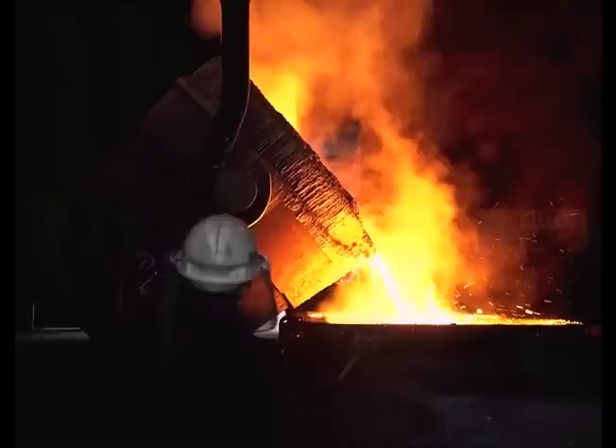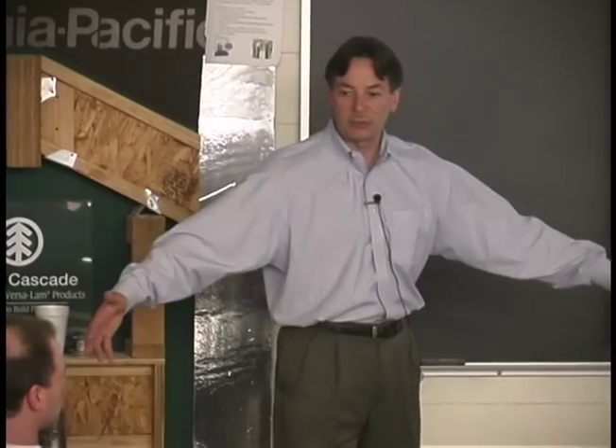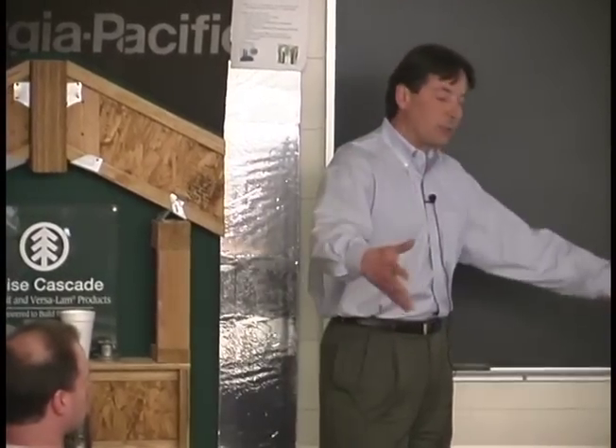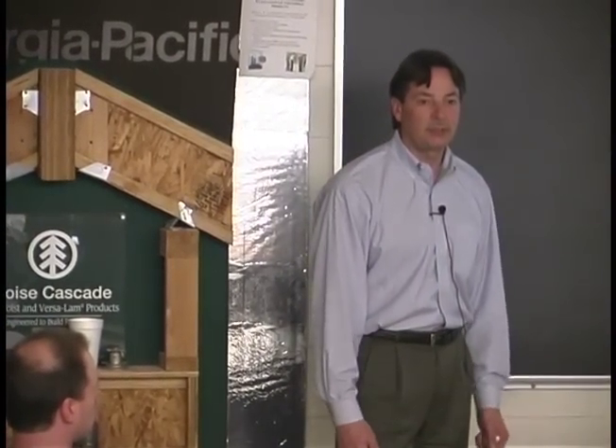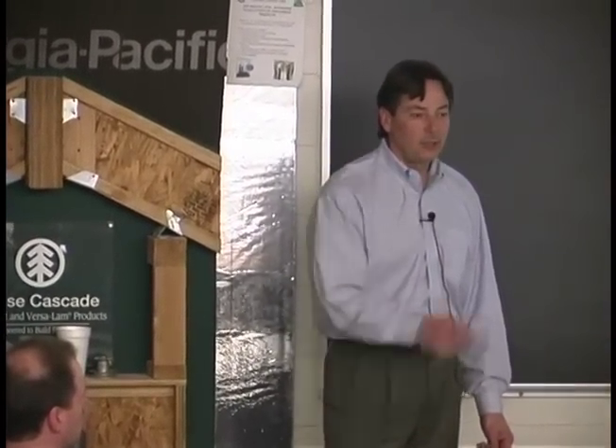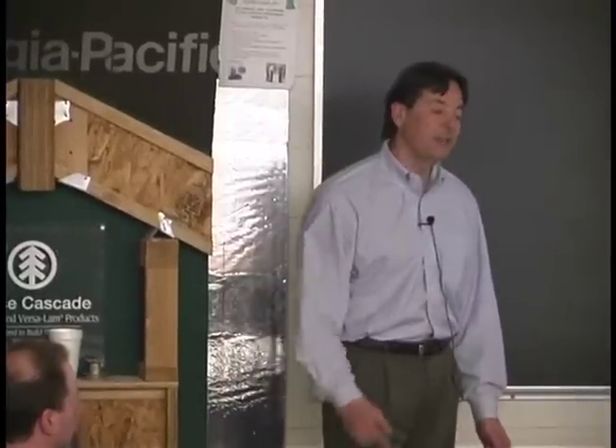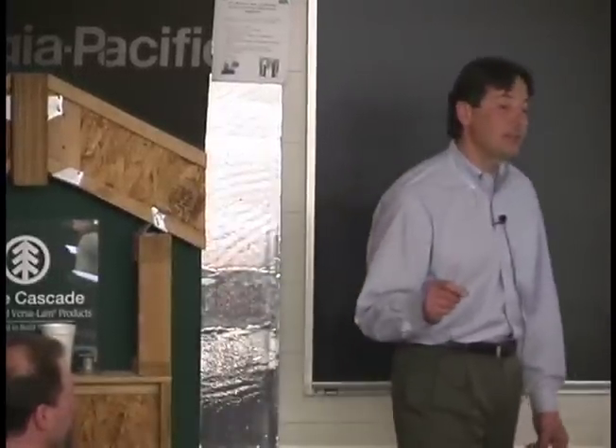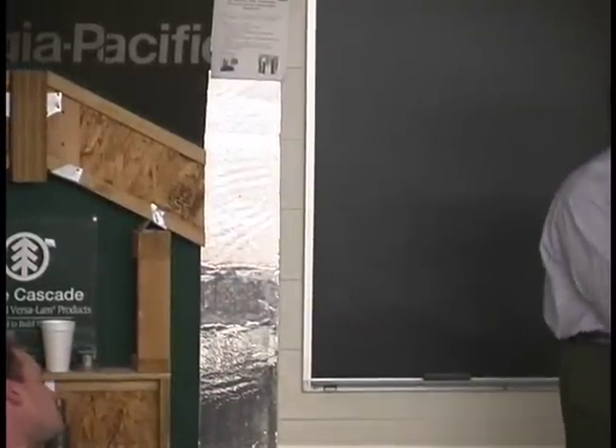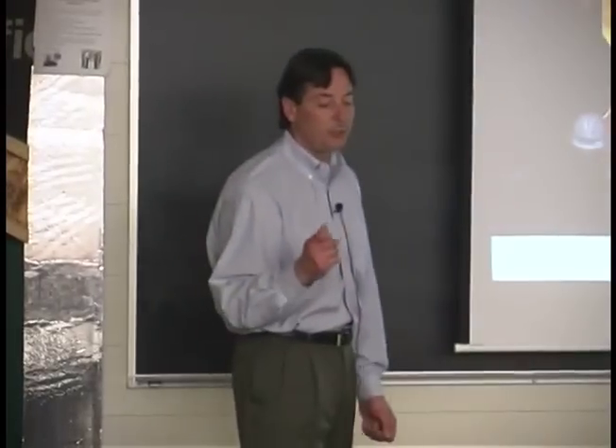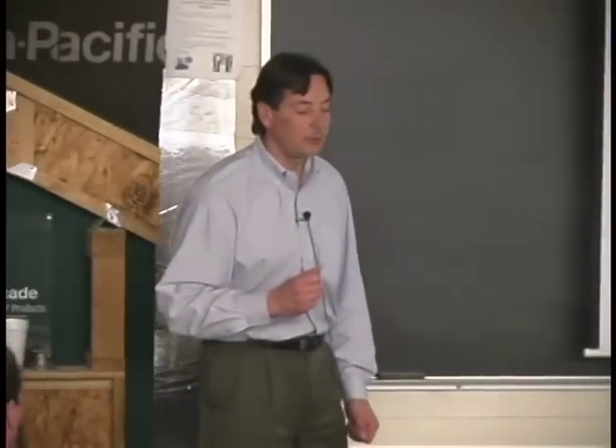This is what it looks like coming out of the ladle. The hot silicon metal is poured into chills. That's exactly what it does in these big flat slabs, is chill. And then they drop it on the ground. It shatters like glass. That starts the crushing process. They crush it to that size, and they'll take it even further. They'll take it from that size all the way down to 10 micron in size, which is pretty damn fine. They use that in ceramics.